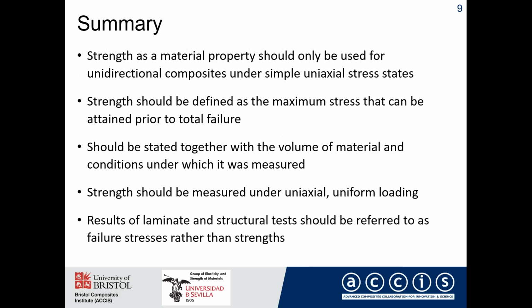So in summary then, we would argue that strength as a material property should only be used for unidirectional composites under simple uniaxial stress states, and that strength should be defined as the maximum stress that can be attained prior to total failure. It should be stated together with the volume of material and the conditions under which it was measured, and the strength should be measured under uniaxial uniform loading. And the results of laminate and structural tests should be referred to as failure stresses rather than strengths.